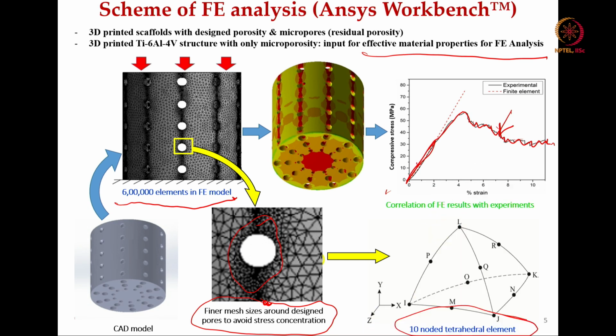From this initial linear part, you can find the slope, and the slope shows you the elastic modulus. What is the dotted line? The dotted line is a finite element approximation. What is the thick line? The thick line is your experimental results. Here finite element analysis can only provide you the linear response part, not the non-linear response part, because here the model is a linear elastic model.